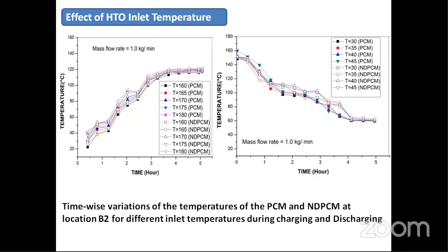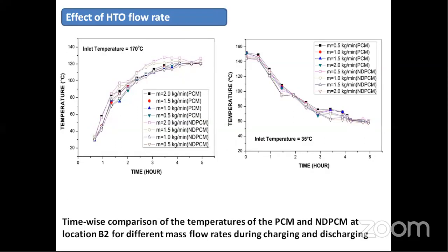The next one, the effect of heat transfer oil flow rate. Melting time was decreased by 20% for PCM and 30% for NDPCM when the flow rate increased from 0.5 kg per minute to 2 kg per minute. The solidification time reduced by 19% for PCM and 20% for NDPCM when the flow rate increased from 0.5 to 2 kg per minute.